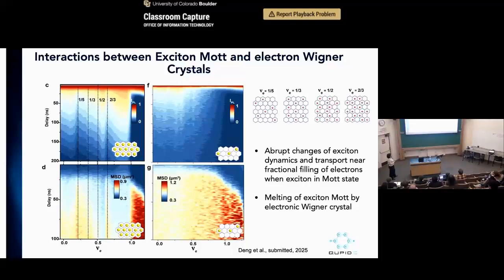In particular, we are interested in the strongly correlated limit where you have a very high density of excitons. On the left, I prepare an exciton Mott insulator on top of the charge. In the middle, I compare the case of very dilute excitons, so there's no correlation between excitons. On the top row, I plot the lifetime, and on the bottom, I plot the transport, the MSD. Initially, you can see that when excitons are strongly correlated, they're much more sensitive to charge orders compared to when the excitons are not correlated. When excitons are not correlated, the changes seem to be more homogeneous or monotonic. But when excitons are correlated, you can see sharp changes around these charge orders.